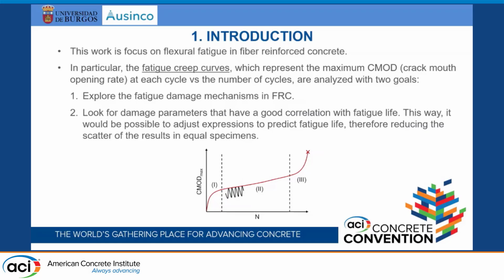And with these curves, we want to analyze them with 2 main goals: explore the damage mechanisms that appear in fiber-reinforced concrete and how they evolve. And the other goal is to look for damage parameters in these curves that can let us predict the fatigue life of the specimens and thus reduce the scatter when predicting fatigue life.